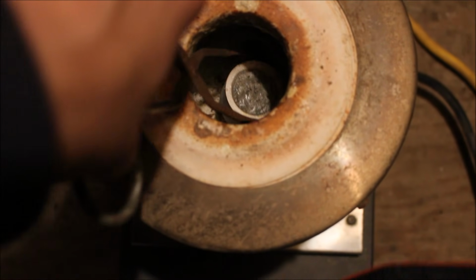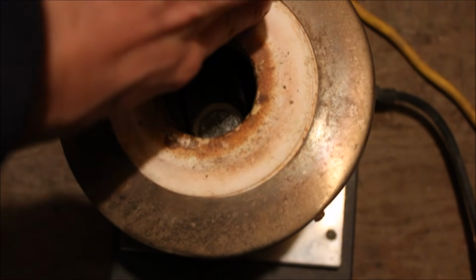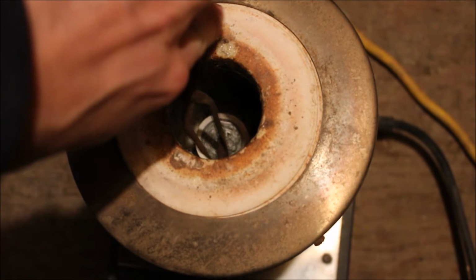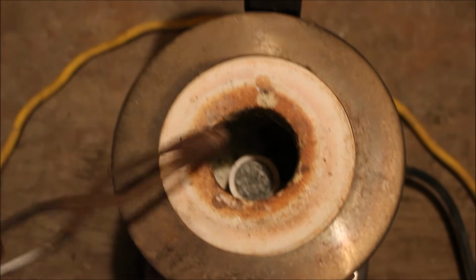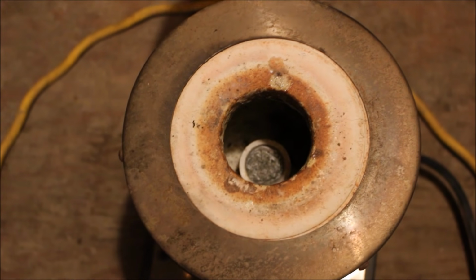Alright, here it goes. I'm going to put it inside this furnace, just like I did the silver when I was making that ring. And I'm just going to leave the lid open so that air can get in there and oxidize the lead. And once this gets to about 1500 degrees, lead oxide will melt and start flowing into the cupel.